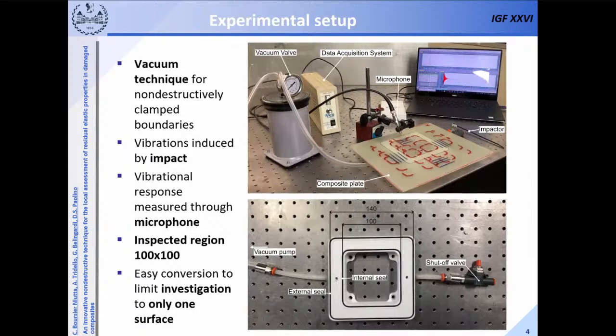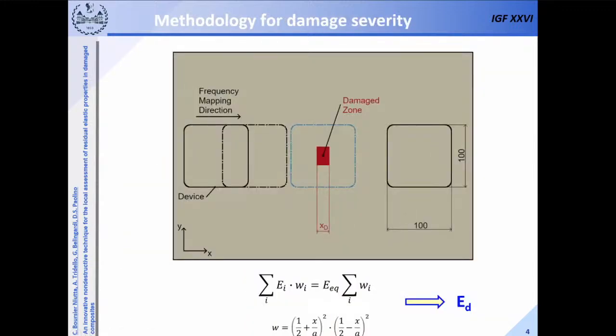Here you can see the experimental setup, where in order to non-destructively clamp the boundaries, the vacuum is adopted, and the region under investigation is the one comprised within the internal seal. The technique is also characterized by a mapping procedure, where the device is moved on the plate in order to obtain different measures of the frequency. And this also highlights that the frequency reduction was proportional to the participation of the damage to the mode shape. The higher the modal participation of the damage, the higher the reduction of the frequency. And from this observation, we were able to calculate the elastic properties specifically of the damaged region.